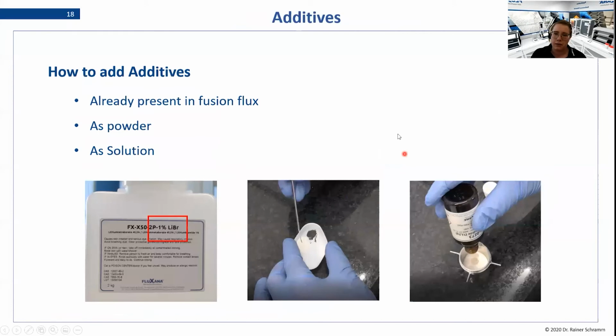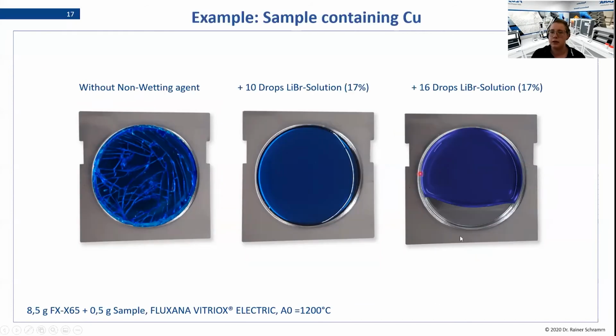And the bead will shrink in the mold so much that it cannot fill the mold anymore. Now there are some samples where you're having the problem that you have either this or that. So either you will have a break or you will have a half moon, and you will never get the exact amount of halogen you need to get this kind of nice bead. Then keep in mind that in XRF it's only important to have the correct ratio, and that means that if you just higher the amount of sample and your flux, you will be able to fill the mold again here.